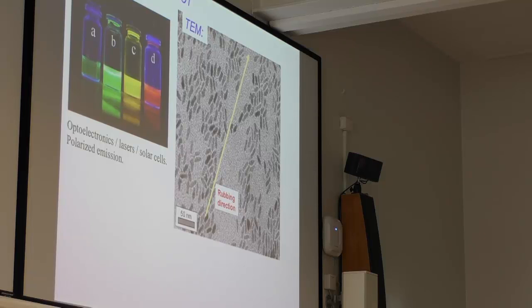Another story, which also goes on materials of interest to organic electronics: cadmium selenide, which is famous for this series of solutions, right, where you can see that their colors are size dependent. As I suppose you all know, this is a quantum confinement effect. If you look at these rods with an electron microscope, you will typically see something like this, where it has been deposited onto a substrate, gently rubbed like this. The rubbing direction is like this, and you can see that there is indeed some alignment of this cadmium selenide with the rubbing direction.